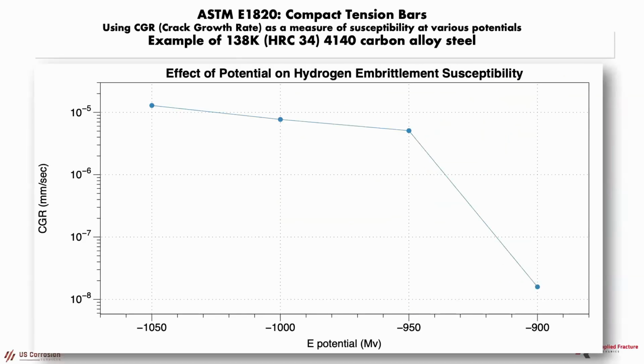So here's an example of looking at the effect of the potential and how different potentials work as well. As part of this test methodology, we want to understand what happens if you have either an impressed current or if you have anodes. And depending on the current that your material is actually seeing, you have a huge impact on the crack growth rate and essentially on the embrittlement susceptibility.